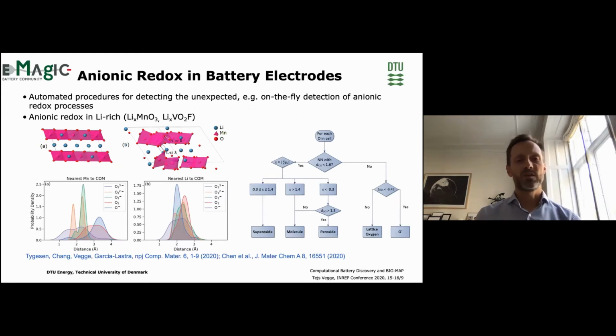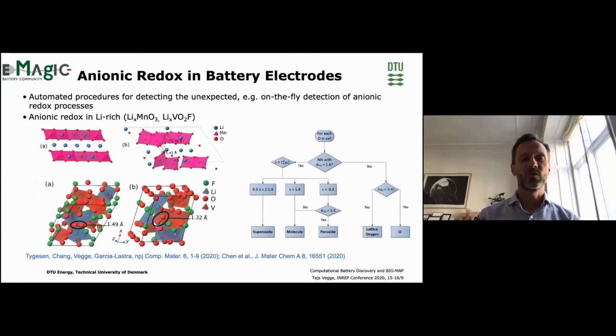What we discover is, once we have oxygen pairs, what is the distance between the oxygen pairs? If it's below a certain cutoff, like 1.6 angstrom, we then analyze the magnetic moments, and based on those 2 properties alone, we can determine whether it's a peroxide, molecular oxygen, or superoxide species that we have in the system. You can also see what's lattice oxygen. This is important to know what is the local environment surrounding the cations in the system, but also that we can transfer this methodology to the disordered rock salts that we talked about before, and see that even in those systems, we actually have the onset of anionic redox.